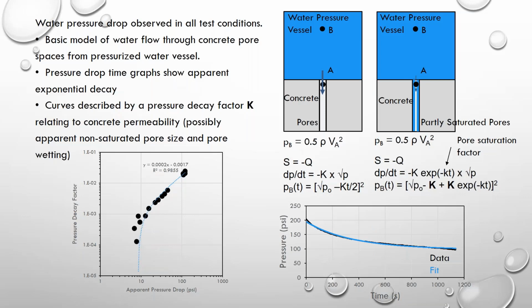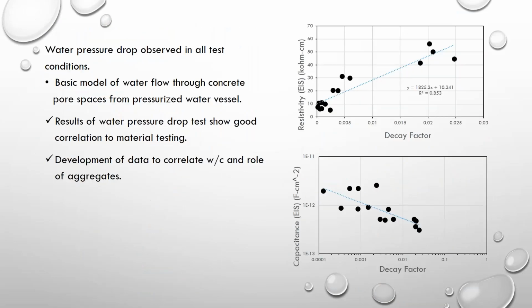And what we're seeing that is very interesting to us is that the dimensions for this K factor relate to the pore size and the pore saturation, which we would like to use to identify conditions of the concrete and characterize the concrete. So here's a graph showing a little bit of correlation we're seeing. Again, the K factor characterizing that pressure drop, and we plot it versus resistivity, for example. And wet resistivity is a common metric we use to identify durability for concrete. And we see that the resistivity and decay factor K for a water pressure drop correspond very, very well. And what we want to do is get a K factor again, try to ascribe that factor to the apparent pore size and pore size distribution. Likewise, for other electrical conditions, capacitance also shows good correlation with the K factor.